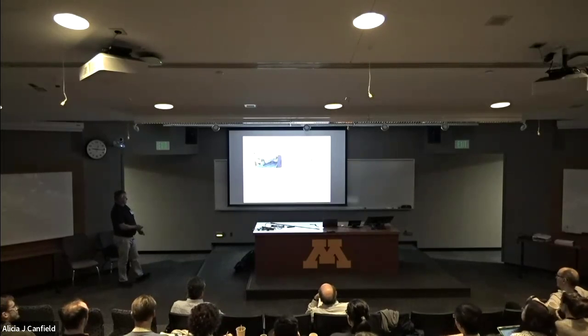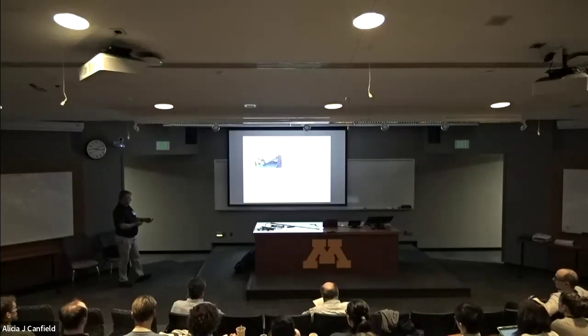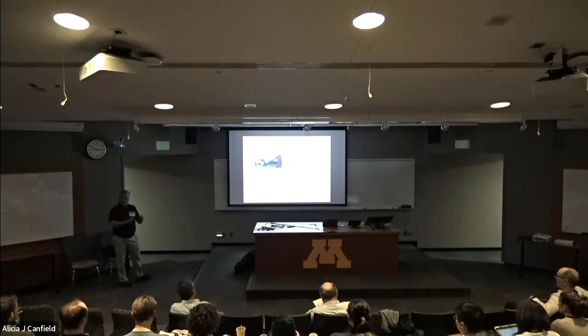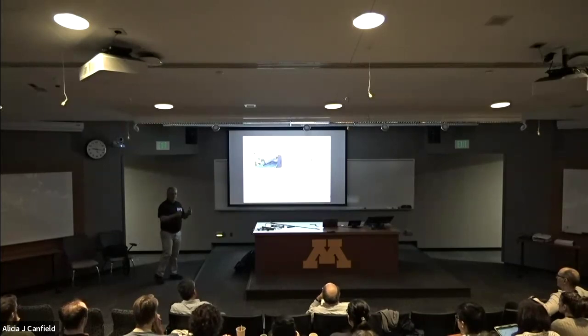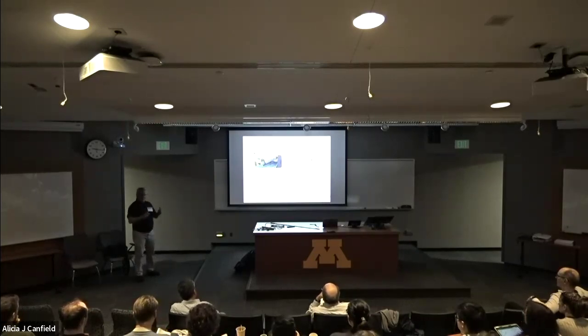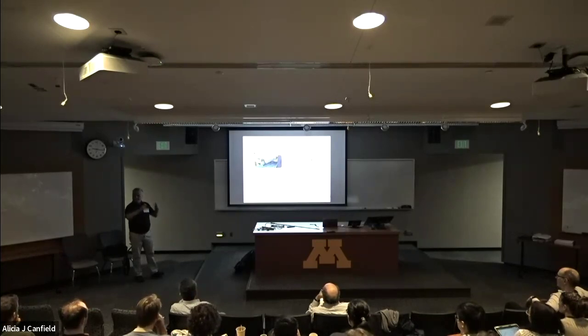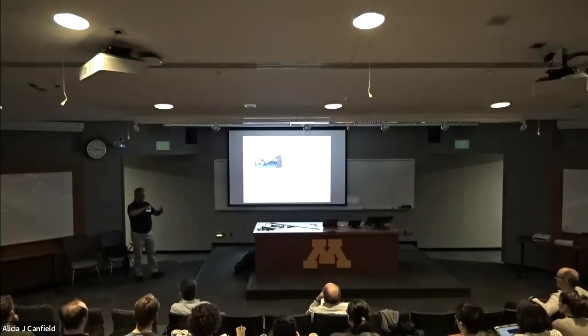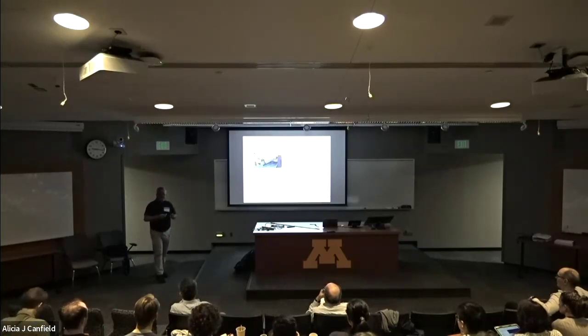So what we did is we went to the SIRIUS 2.5 megavolt electron accelerator in Paris. And that's a very special place because very high energy electrons make almost elastic collisions with solids. So they are unable to dump very much energy in at all. So the chance that these high energy electrons do anything to the material is extremely low. With a very small cross section, some of them will displace atoms. And they create what are called Frenkel pairs, which are vacancies or interstitial atoms. The interstitials will often migrate as you warm the sample up, but very often you leave the vacancies in place.